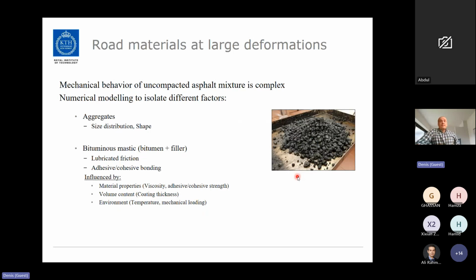So that was a little bit on experimental tools to study mechanical behavior of asphalt mixture at large deformations, but this process is very complex and we have a lot of parameters which affect the response. We have, of course, aggregate parameters in terms of size distribution and shape, and by far aggregate parameters, aggregates being the main component in asphalt materials, their parameters dominate response at uncompacted state.